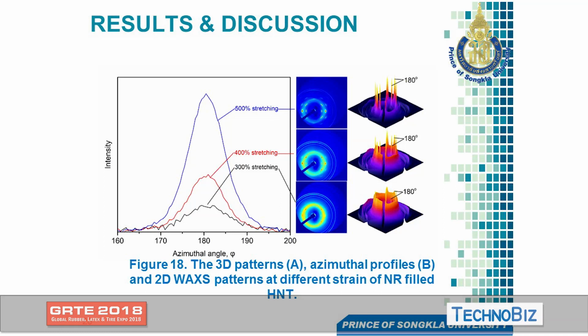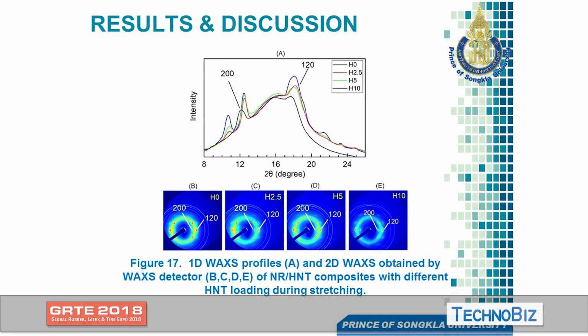Yes, once we pick up at certain angles, we can see here that once we increase the stretching or strain, a distinct peak occurred. That means that crystallization occurs after being stretched. This is very common for natural rubbers. But over here, the peaks are totally different compared to the normal case without any use of the HNT.